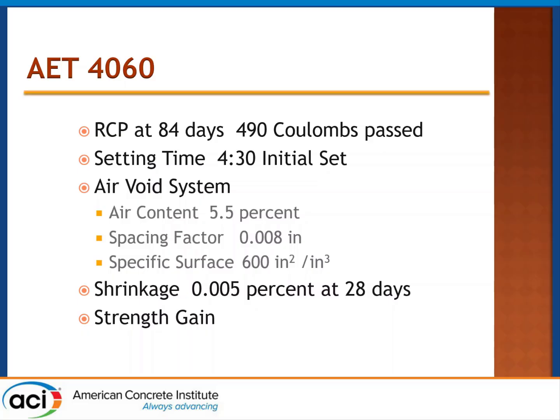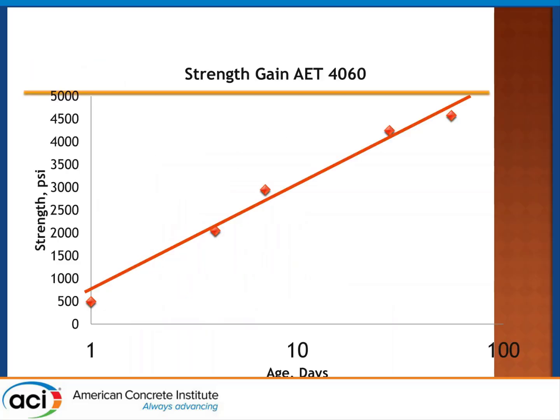And he ran a bunch of tests for us, and we got rapid chloride permeability at about 490 coulombs passed. Setting time was reasonable because we knew what we were doing. And this was based on concretes we've been doing for mass concrete that were about 15% by mass Portland cement, about 600, about 580, I should say, total cementitious. Air content looked good, and the strength gain was fairly respectable. Out at 90 days, we're about 4,500, and these are laboratory cured cylinders. And we're going to come back to laboratory cured cylinders in a minute.